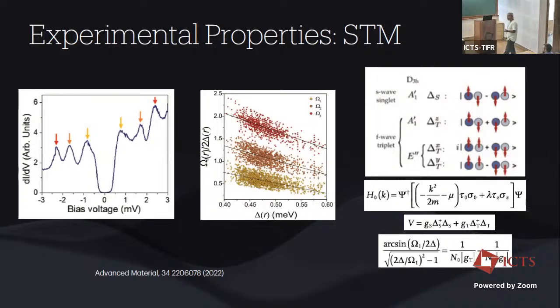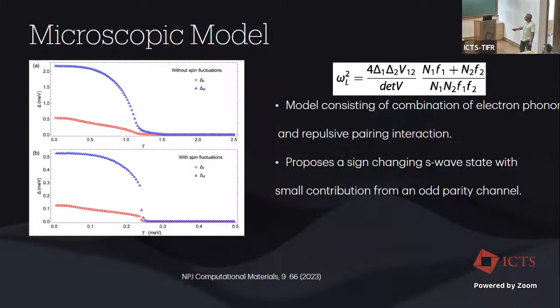First principle calculations had already shown before, by Igor Mazin's group and others, that if you look at the susceptibilities in the system from first principle, there are strong spin fluctuations in the system, which are not present for the bulk material. So the question was, how do we understand any unconventional contribution to the pairing? So this was a theoretical work by Igor Mazin's group and Dan Achterberg, where they essentially showed that if you start off with a pairing mechanism where you consider the pairing is due to electron-phonon interactions in your system, then for this pairing mechanism, you can show that the gap on the gamma-centered pocket is much smaller than the superconducting gap that you have on those K-centered pockets.